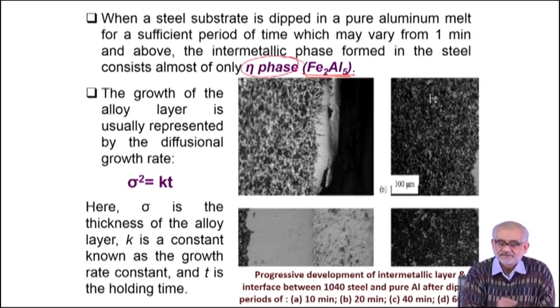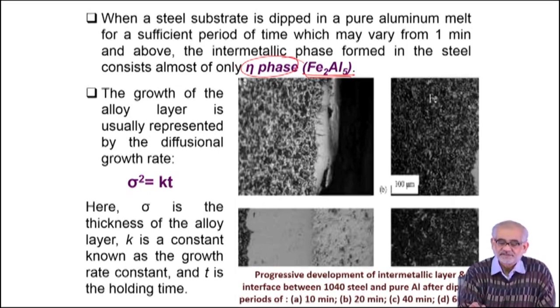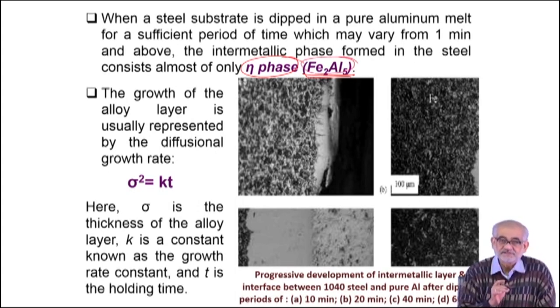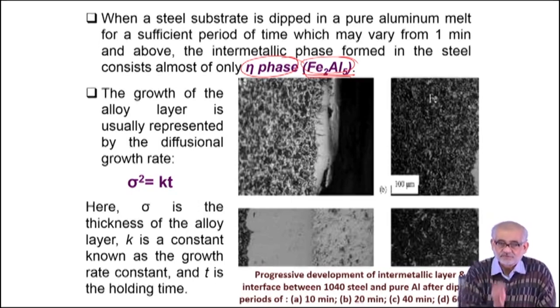Instead, they are known to form certain intermetallic phases. These intermetallic phases are easy to understand when you refer to the corresponding binary phase diagrams — say iron-aluminium, nickel-aluminium, or titanium-aluminium. Multiple intermetallic phases are possible in these binary systems. In the case of iron, one such eta phase that forms is an iron aluminide. This is both beneficial and a matter of concern — beneficial because these phases are extremely stable with very high melting temperatures and prevent oxygen ingression or cation movement outward, forming a barrier layer.